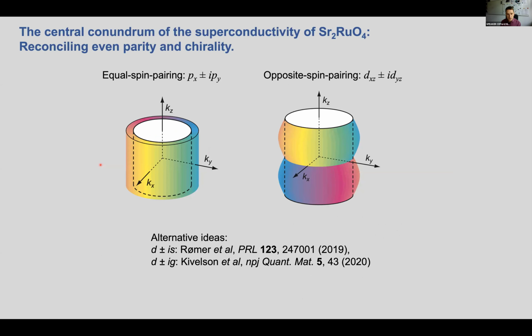So this leaves us with a conundrum for strontium ruthenate. And this is the central conundrum of the superconductivity of strontium ruthenate: how do we reconcile chirality with even parity pairing? Under the tetragonal symmetry of strontium ruthenate, the natural candidate to consider is xz plus iyz. However, that has a horizontal line node at kz equals 0.